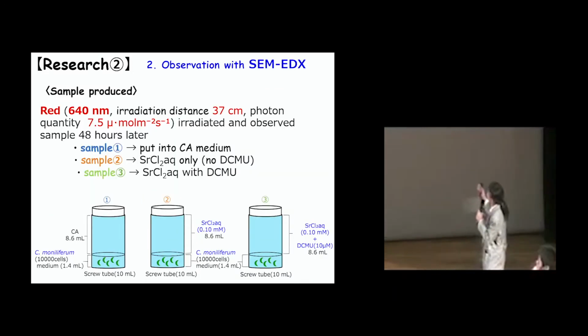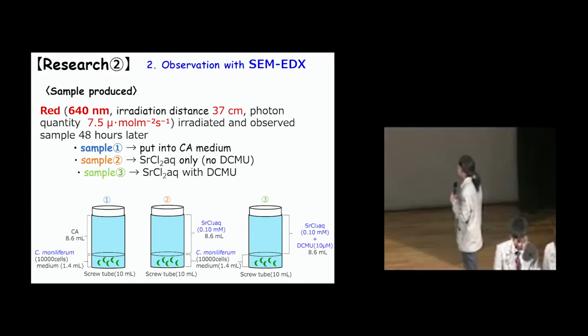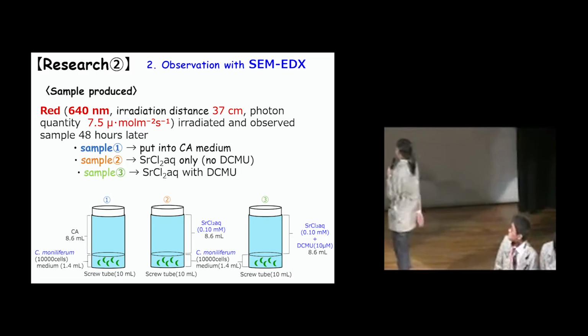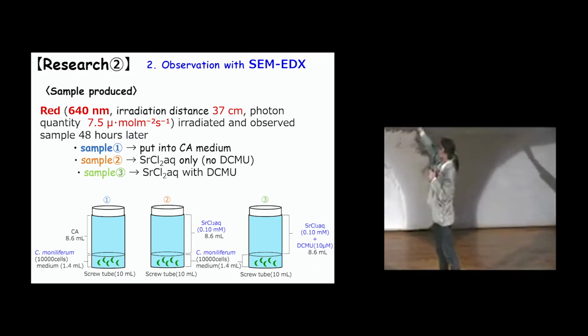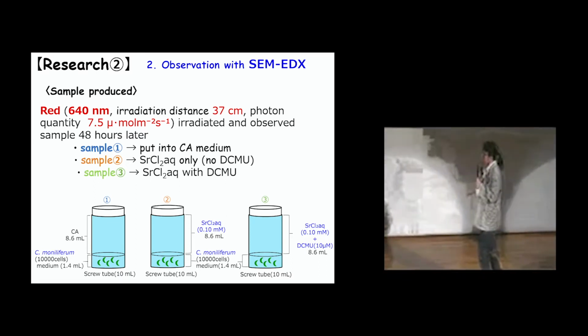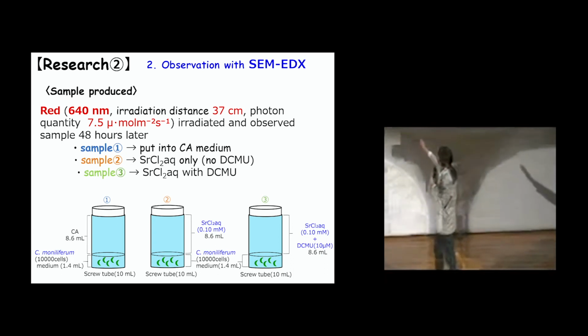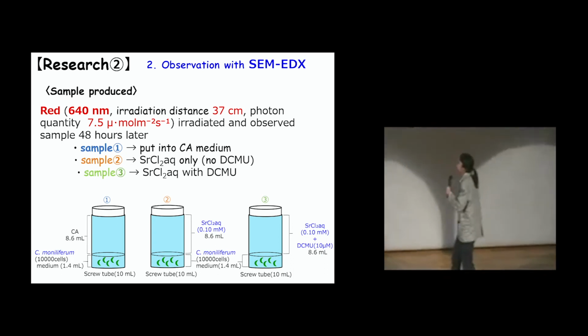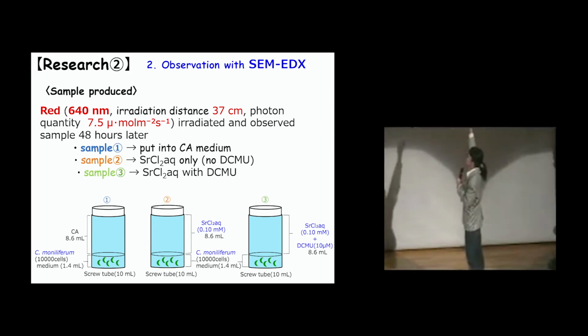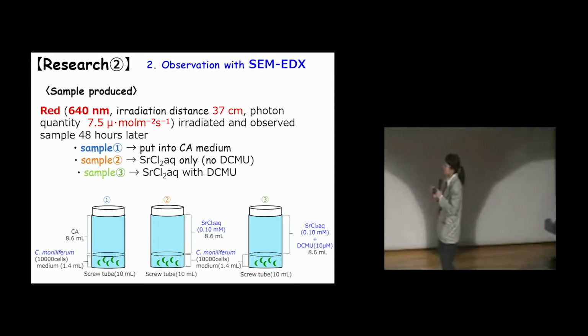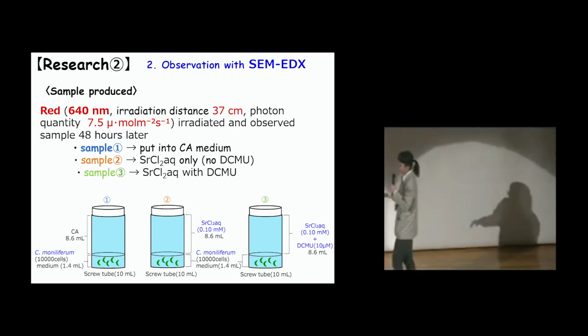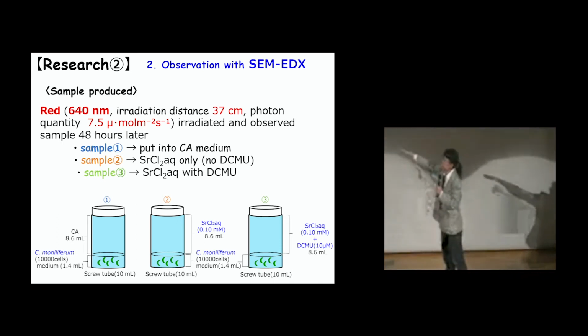2. Observation with SEM EDX. Based on it, we used SEM EDX. We made 3 samples. Sample 1, put into CA medium. Sample 2, strontium chloride aqueous solution only, no DCMU. Sample 3, strontium chloride aqueous solution with DCMU. In addition, we used the same medium culture of Closterium moniliferum equally divided.